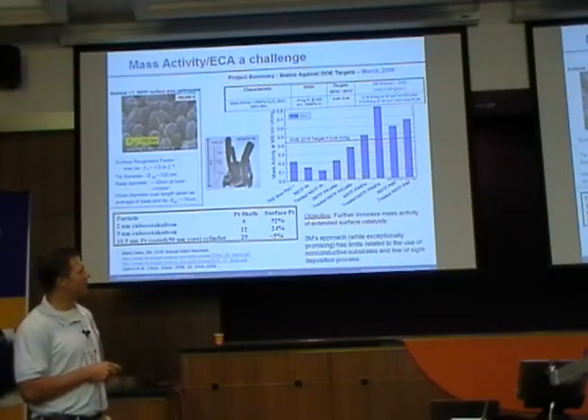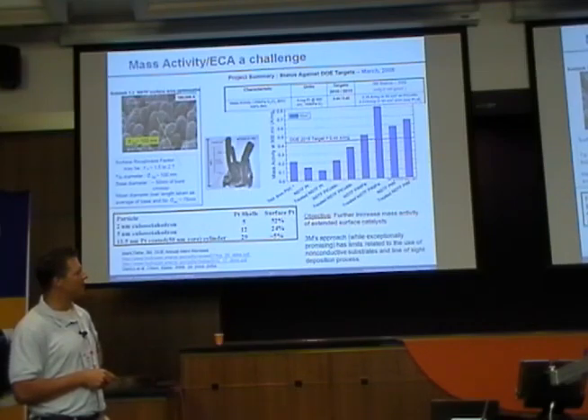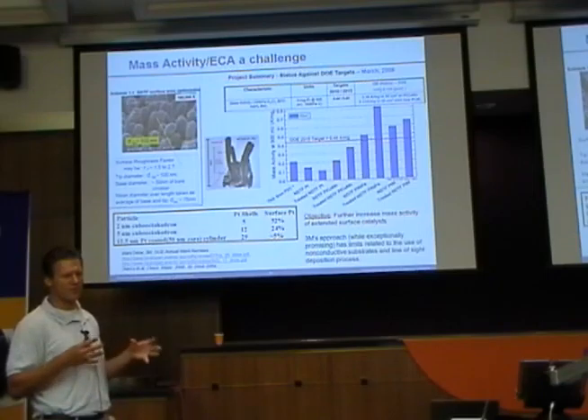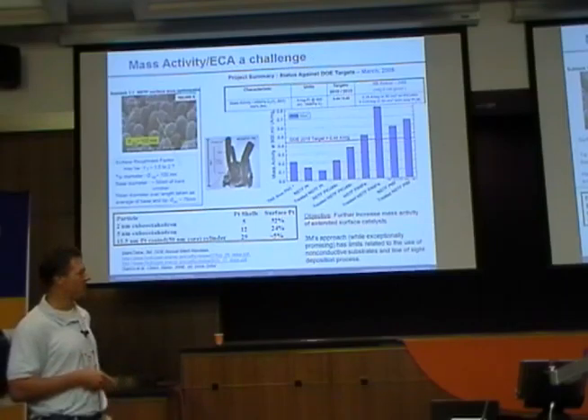And so if I look at these materials and do the math on them, I can assume that they're about a 12.5 nanometer platinum coating on a 50 nanometer core cylinder. So that's about 29 shells of platinum that has a surface roughness of about 2. And so only about 5% of the platinum is actually on the surface. So even though these have extremely high specific activities of each surface atom, they don't have very many of the atoms on the surface, only 1 in 20.